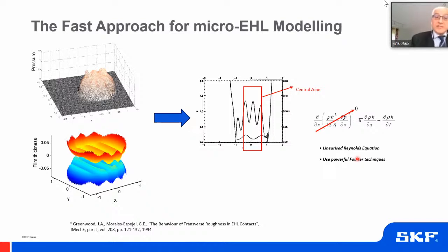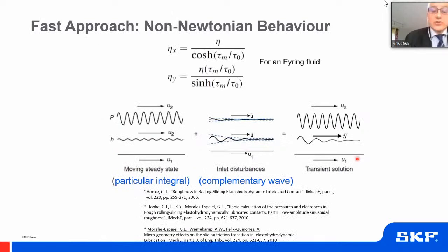The reality is more complex than this because if you want to deal with non-Newtonian fluid, immediately you realize that you cannot totally remove the Poiseuille flow. Parts will have to remain in order to model the non-Newtonian behavior. So we need to calculate the equivalent viscosities in the two directions, but also more important, the overall solution for the ripples is made of two important parts. One is what we call the moving steady state or the particular integral, and this is basically describing the deformation of the roughness when it goes into the contact and the generation of these pressure ripples.